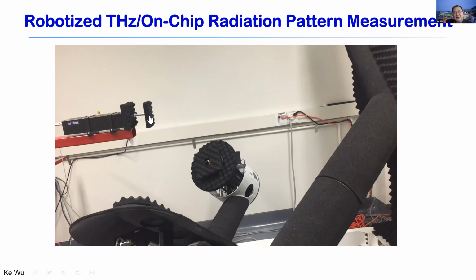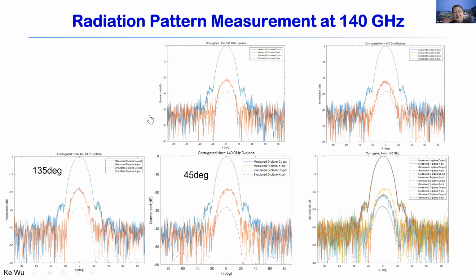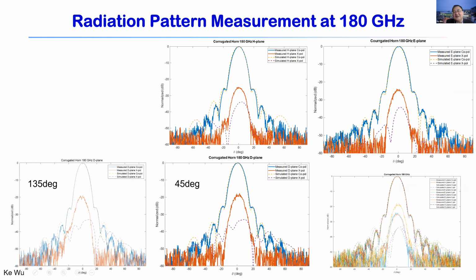In this case, we use a horn antenna system for this corrugated horn measurement. We also measure at 140 gigahertz. You see the co-pole and cross-pole; measurement and simulation agree very well, except the cross-pole has a little bit of deviation, but that's acceptable because of certain conditions we cannot really consider in the actual measurements. This is 180 gigahertz for different conditions, which again confirmed our measurement and simulation results.